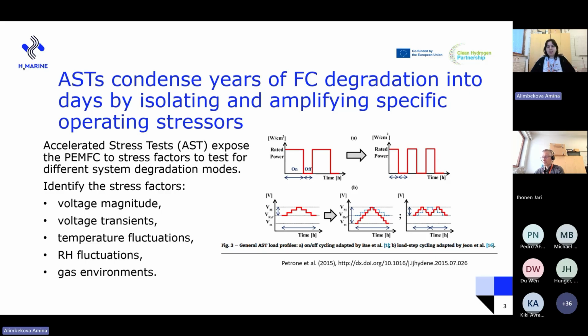The catalyst degradation primarily proceeds via two mechanisms within PEM fuel cells: platinum dissolution and migration, or platinum particle coarsening and growth via Ostwald ripening. These two phenomena are quite dependent on voltage magnitude and the frequency of the voltage transients.